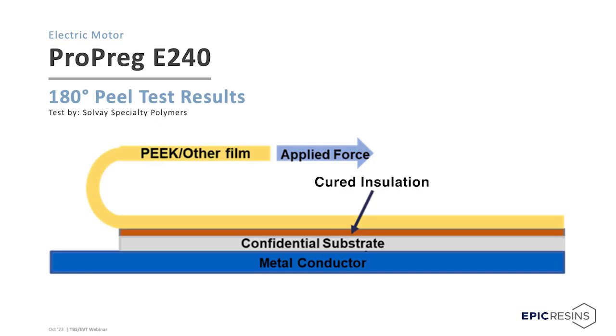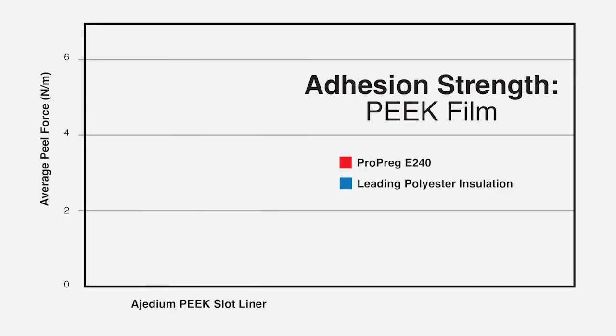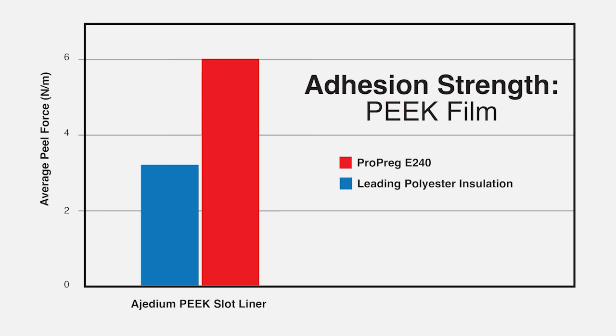The unique surface tension of ProPreg E240 significantly improves the adhesion to PEEK-coated conductor wire and slot liners compared to the leading polyester. The analysis conducted to test adhesion was a 180-degree peel test. As you can see in the illustration, a PEEK film is adhered to the metal conductor substrate using ProPreg E240 or polyester insulation. The PEEK film is then pulled at a 180-degree angle while the metal conductor is held in place. In the 180-degree peel test, you see in the graph that ProPreg E240 obtains at least double the adhesion compared to the leading polyester.